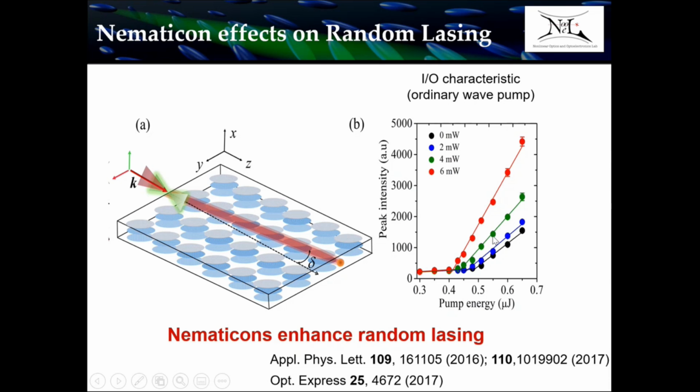So we go from black to blue to green to red by increasing the soliton power by a few milliwatts. So we are able to control the emission and improve the amplification of the random laser by increasing the power from 0 milliwatt to 6 milliwatts in a near-infrared beam which forms an optically induced waveguide.